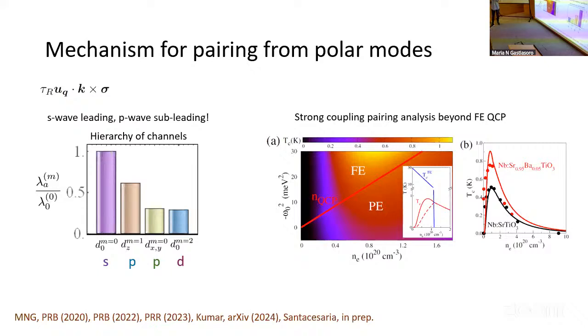And without going into details, then it was like, okay, let's take a material and really work out the entire theory and see how much of it agrees. So the dots are the experiment, and the line is this theoretical model. We assume that the electrons are coupled to these ferroelectric modes. You have to go through the strong coupling pairing analysis, because there is a quantum critical point. In order to do that, you can no longer do BCS, and you have to do some dynamics with the Eliashberg group and so on. But other than that, it works pretty well.